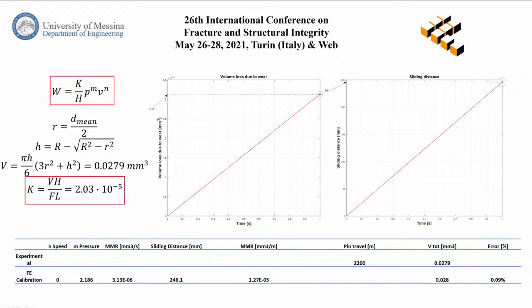So basically the calibration is made in a very simple way. We vary these two values of speed and pressure until the difference between the volume removed from the pin, which we know from the experimental apparatus, is very similar to the finite element model. In this case, we reach this calibration for these two values with an error of 0.09%. So for the calibration we use these two exponents.